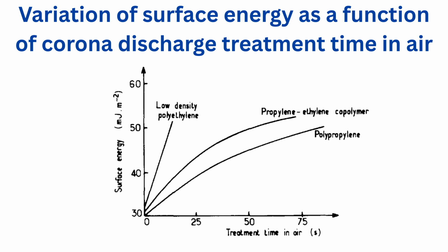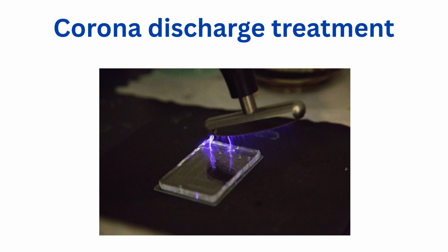Corona discharge treatment of polypropylene sheets under atmospheric pressure shows that the best results are obtained with an oxygen-nitrogen mixture with over 20% oxygen. Alcohols, ketones, and carboxylic acid groups have been identified on the treated surface. The surface energy of treated polypropylene is clearly higher than that of the reference. The adherence level of a polypropylene polyurethane assembly is significantly improved after treatment and depends on the surface oxidation degree.